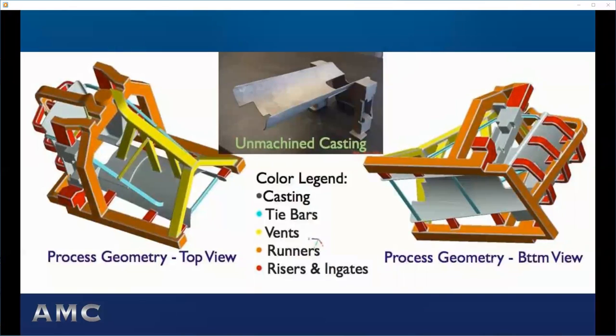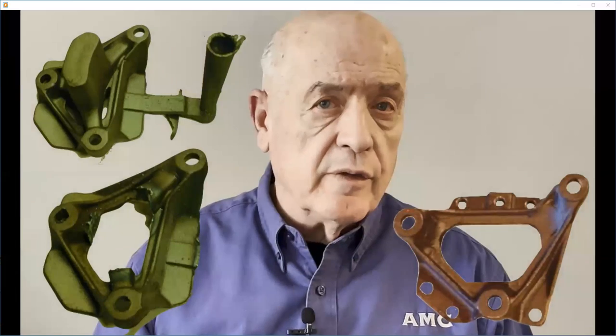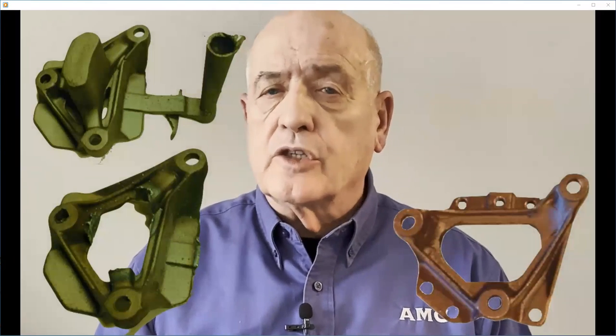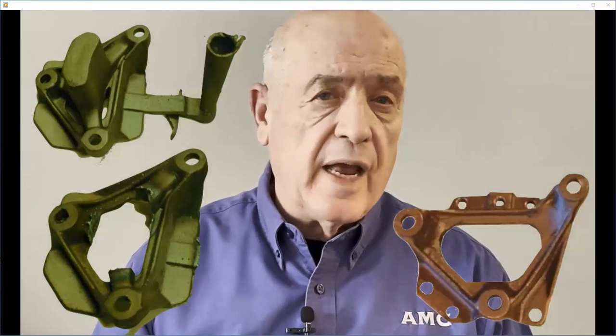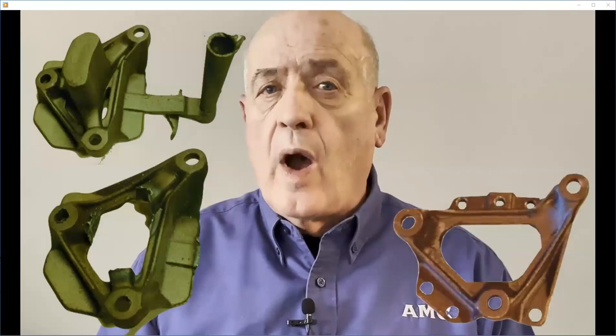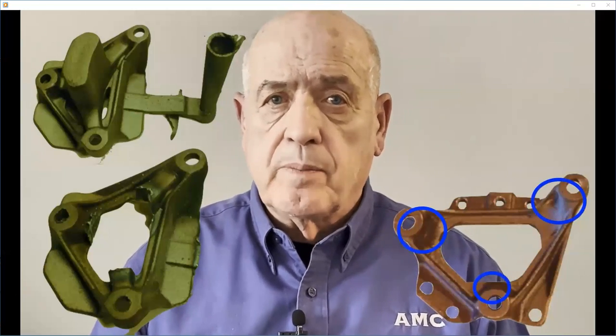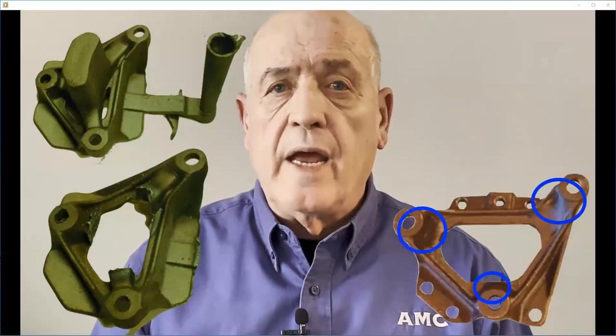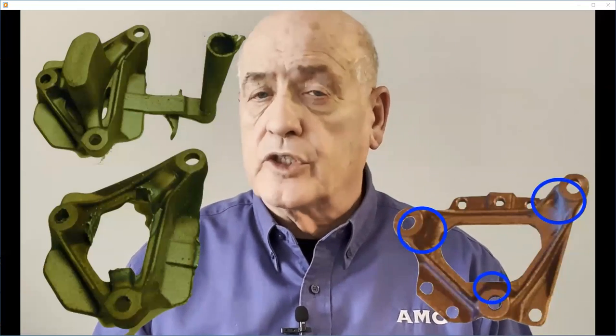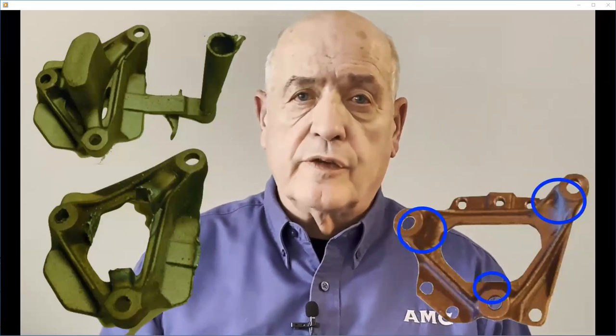The first realization about process interface geometry is that its connections are not as cast. The markers from those connections are manufactured by finishing operators using various means of cutoff and blending. The intent of blending is to make the markers look as much like the surrounding as-cast mold surfaces as required by the casting's dimensional and surface finish specifications. But the marker surfaces don't have the dimensional tolerance capability of the surrounding as-cast mold surfaces.